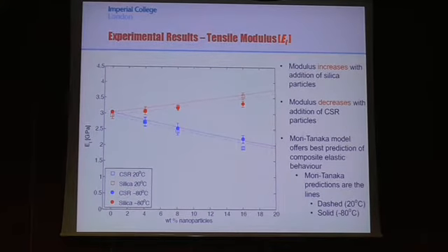So, quickly go through some tensile modulus results, and it's no surprise that when we add the silica nanoparticles to the epoxy, the Young's modulus of the silica is about 70 gigapascals, the Young's modulus of the overall bulk polymer composite goes up, and when we add the compliant CSR particles, the Young's modulus of the composite goes down.